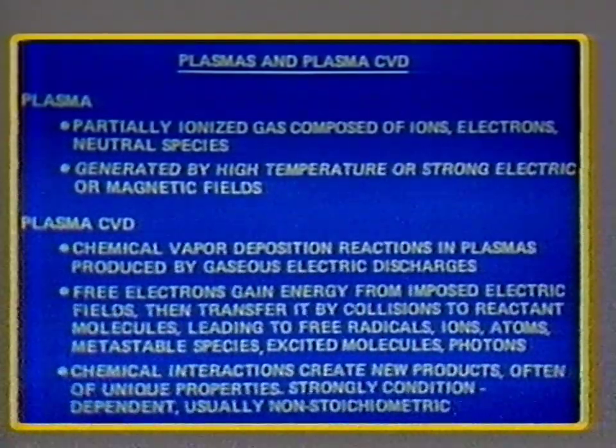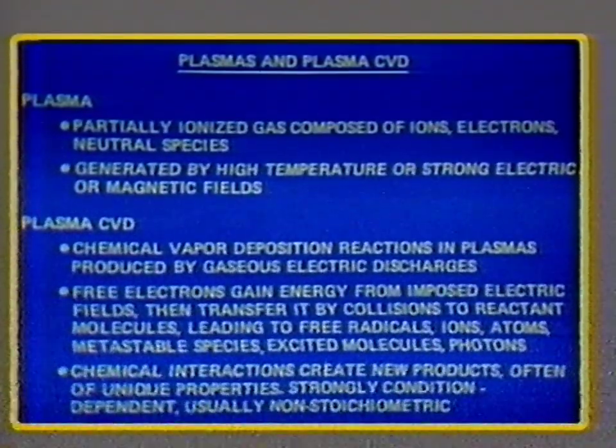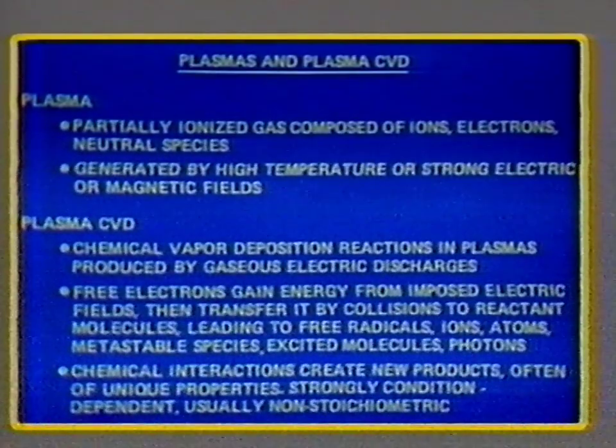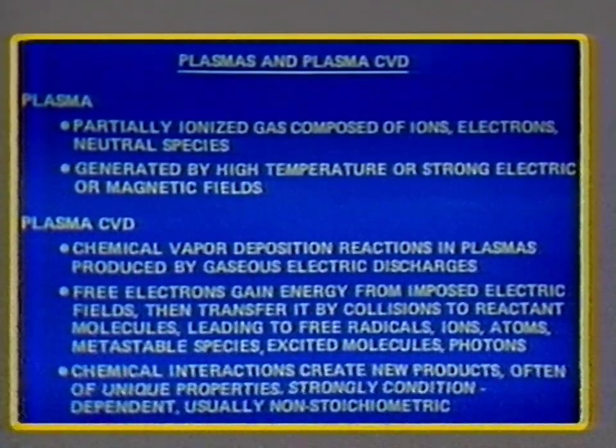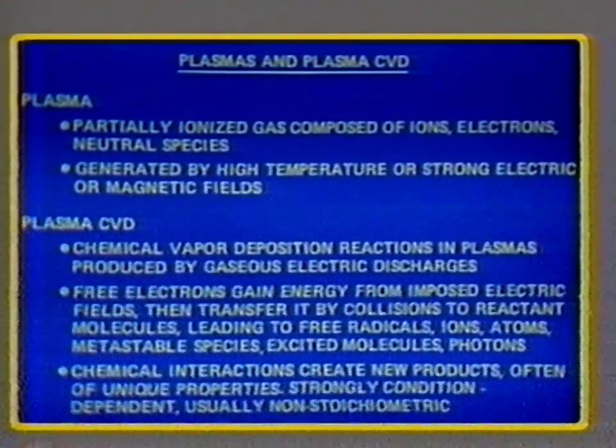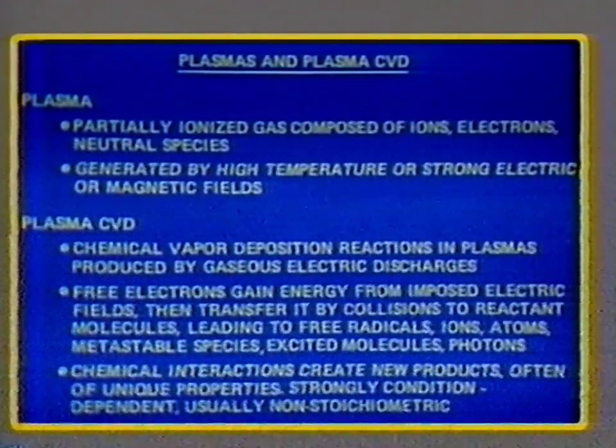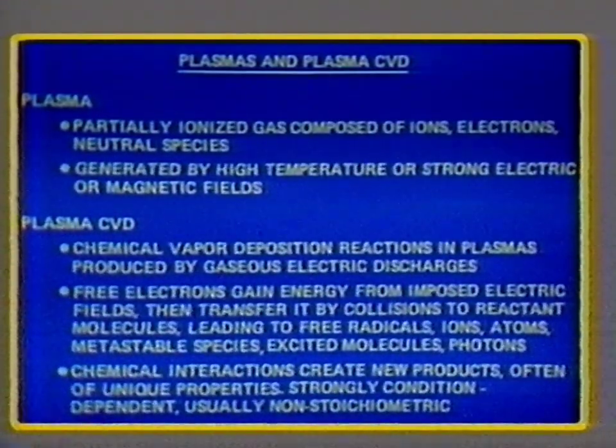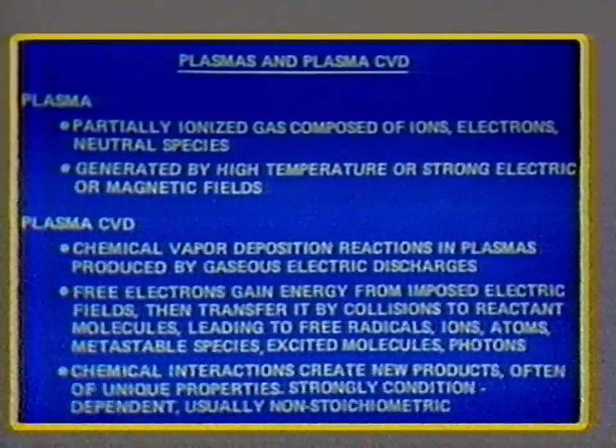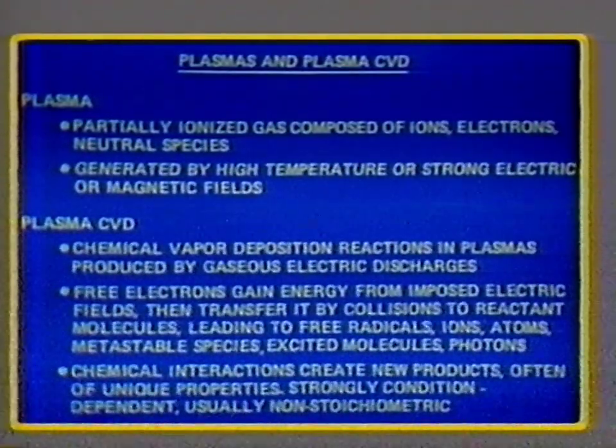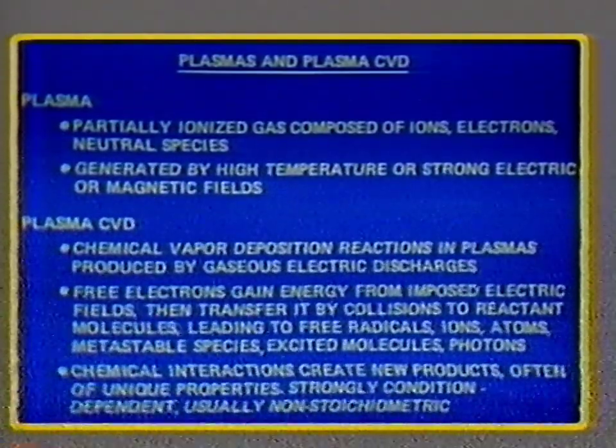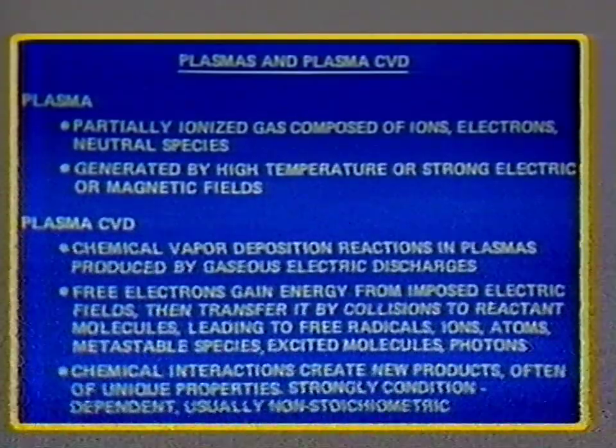Here we have electrons which essentially gain energy from imposed electric fields, transfer that energy kinetically to reactant molecules, and in the process produce a large variety of free radicals, atoms, metastable species, excited molecules, photons, and so on, which then interact and form film materials. Because of the great variety of reactants available, you have also a large possibility of film formation of various types, which can be an advantage, of course, but it also is difficult to control them in a practical sense out in the field to really produce a composition of well-known characterized behavior and repeatedly doing so.